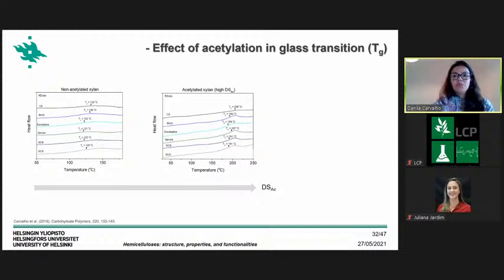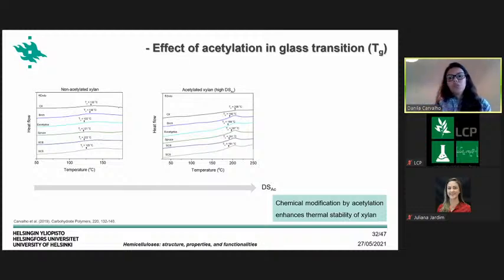Also, there was some beneficial effect on the glass transition by the acetylation. Here we have only the non-acetylated xylan and the xylan acetylated at a high degree. And as a conclusion of this study on the acetylation of the xylan, we could check that the chemical modification by acetylation really enhanced the thermal stability of xylan.